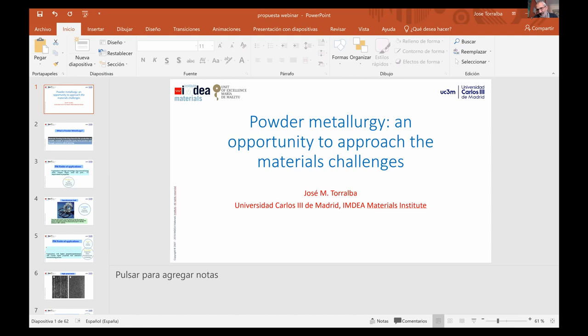So in the case of microwave sintering, I think we are a little bit far from industry, but with spark plasma sintering we are much nearer, because there are some companies which are now working and trying to develop things by spark plasma sintering. Spark plasma sintering, in fact, is like hot isostatic pressing at the beginning. At the beginning of hot isostatic pressing, the problem was the size. It was not possible to produce near net shape parts by hot isostatic pressing, but companies started to produce big ingots of hot isostatic pressed material. What we are trying to do in industry now is to upscale spark plasma sintering at big scale in order to have big blanks that can be machined.